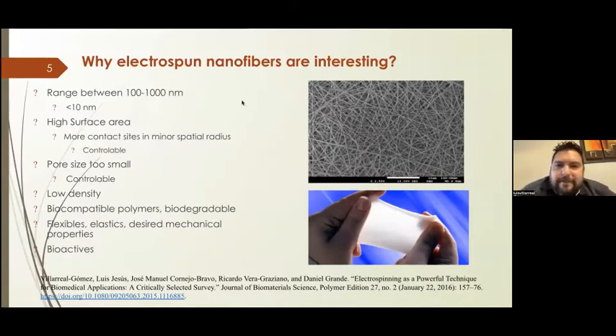Why are electrospun nanofibers interesting? Well, you can prepare these nanofibers in the nanometer scale. There are even a few articles that report fibers less than 10 nanometers. With these nanofibers, you can create mats, as you can see on the right side, and they will have a high surface area. This means more contact sites in a smaller spatial radius. And this property can be controllable. You can also control the pore size.